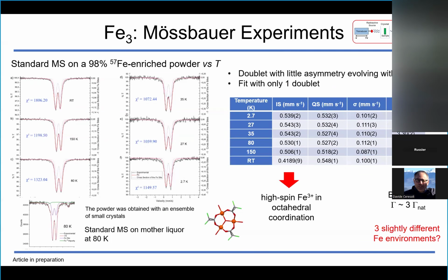But first of all, we did a preliminary study of this spin triangle. In particular, first we studied the powder as a function of the temperature. These are spectra taken with our spectrometer in Florence. We went from room temperature to 80 Kelvin with nitrogen, and then from 80 to 3 Kelvin with helium. The spectrum is a doublet and practically does not change with the temperature. For the fitting, we considered only one doublet, and the result was that the line width is rather broad, something like 3 times the natural line width. This possibly indicates that the molecule has an equilateral geometry, but only an approximate one, so we are sensing 3 slightly different iron environments.